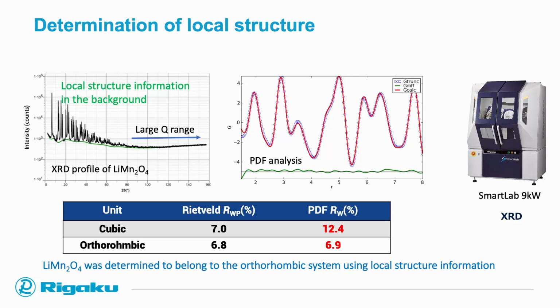However, when you come across some secrets in your diffractogram, for example, as in this case, we see in the Rietveld refinement, we use a cubic unit cell or cubic structure for the lithium manganese oxide, and we see that the quality measure of the Rietveld analysis is not satisfying. We see with the help of the PDF analysis that this structure is actually of orthorhombic nature. So we achieve also with the help of the PDF a much better result.